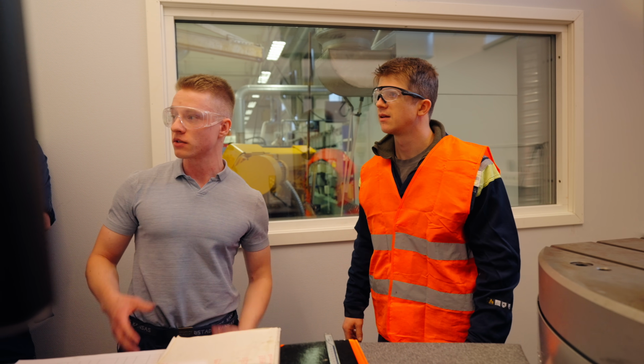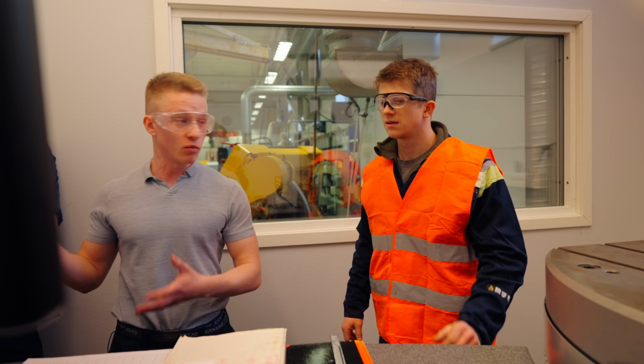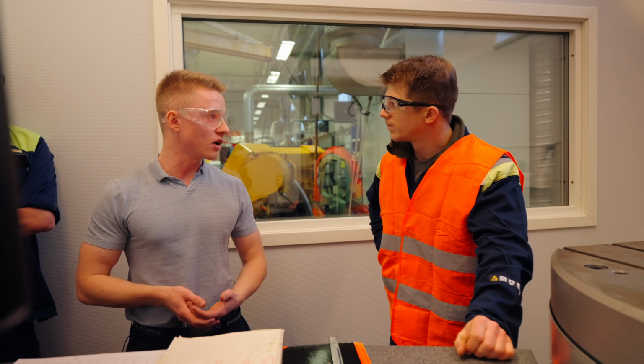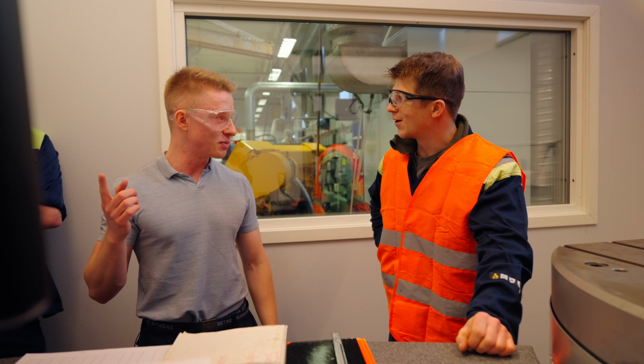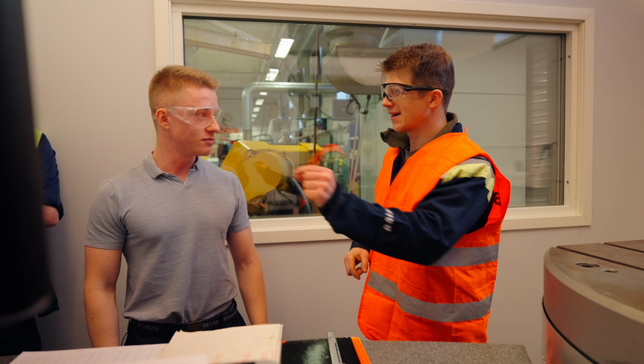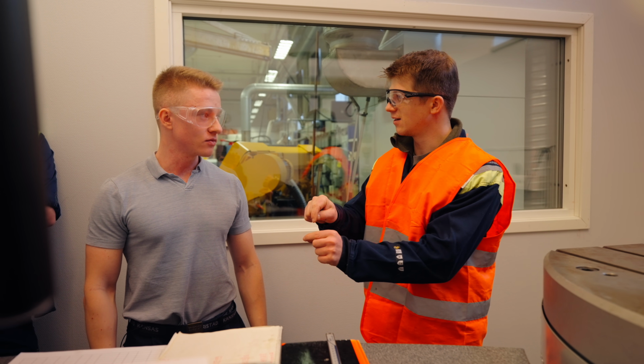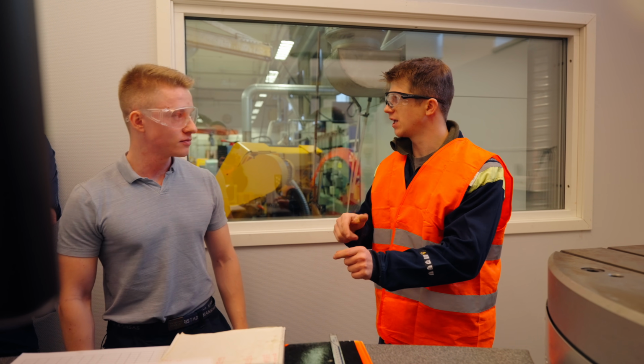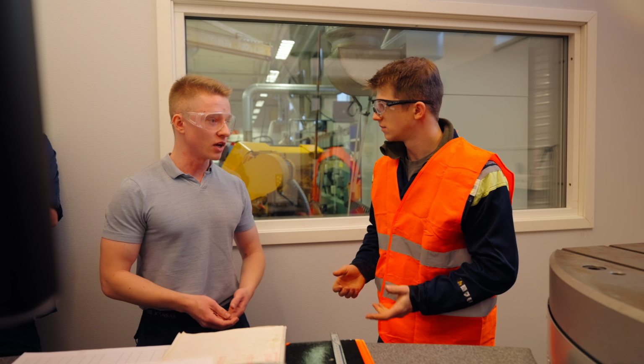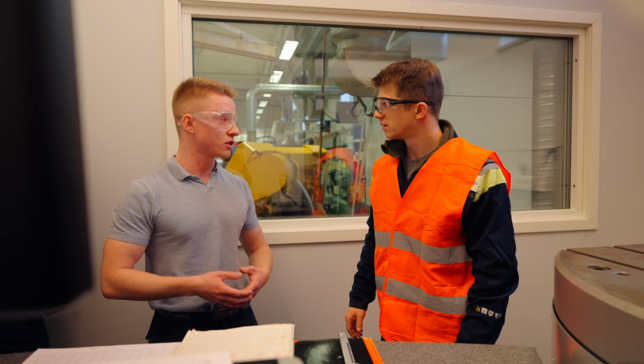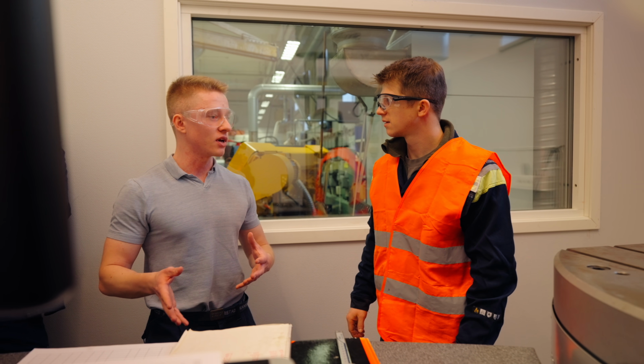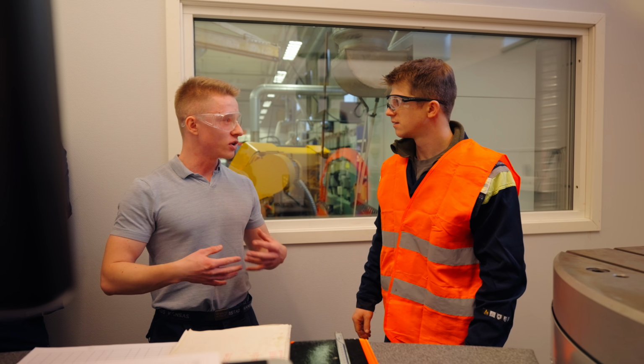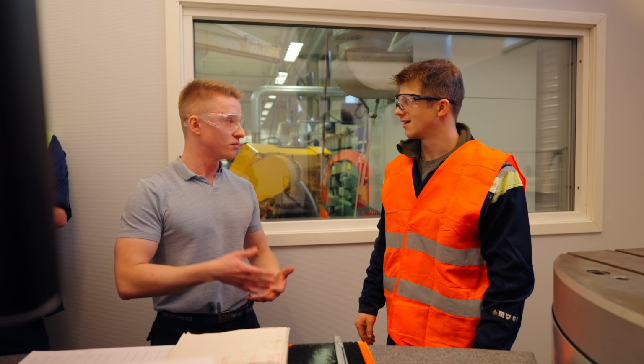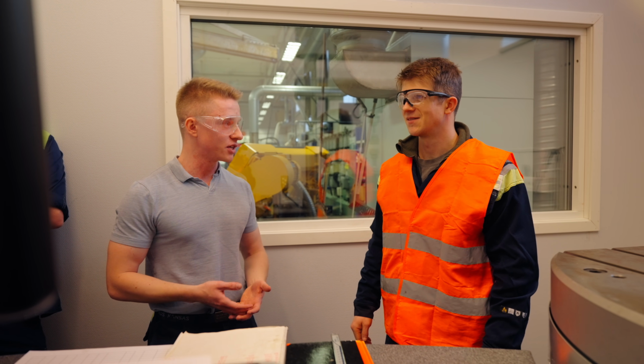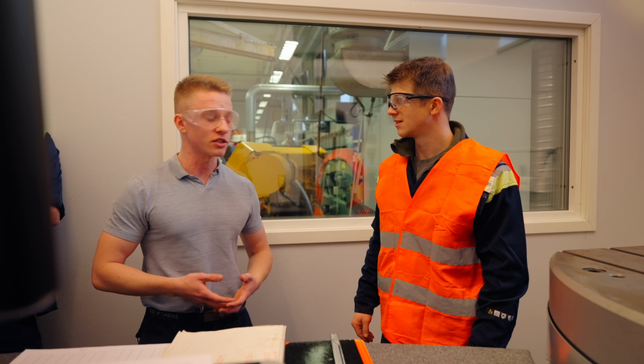Exactly, and this makes actually being able to identify what kind of inclusion it is and actually measure it in our scanning electron microscope that we have. So you'll then take this to the scanning electron microscope, you'll find that little white dot, and you'll go, oh, this inclusion is X, Y, or Z, and we actually find where in the production it has occurred, and in that way we can actually avoid it more and just work to reduce the amount of inclusions inside the material. So this is a continuous improvement.